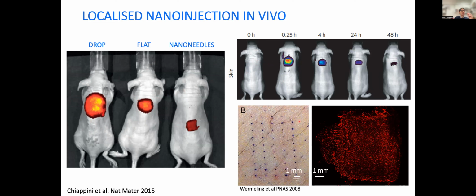Obviously, this is something that you can do with microneedles as well. But the microneedles have a very precise way of delivering only in the vicinity of the individual needle itself. And there is 1 needle every hundreds of microns. That means that in practice, you are delivering a lot of your payload in very few areas within your tissue. And that's not very efficient if you want to transfect the cells that exist in between these very concentrated delivery sites. So you end up having a very high gradient of your delivered payload.